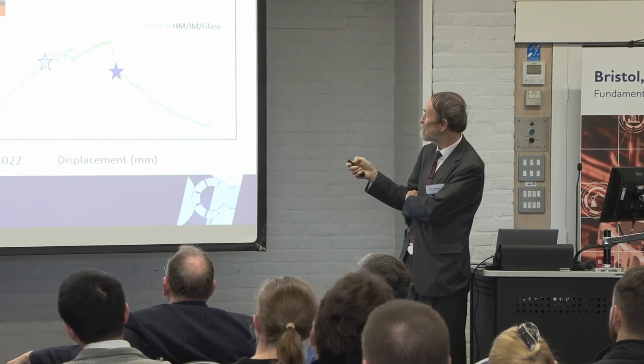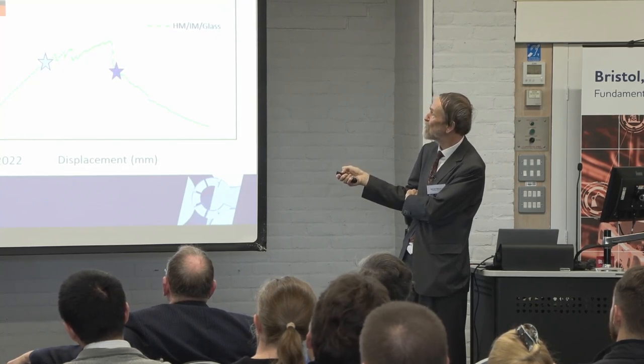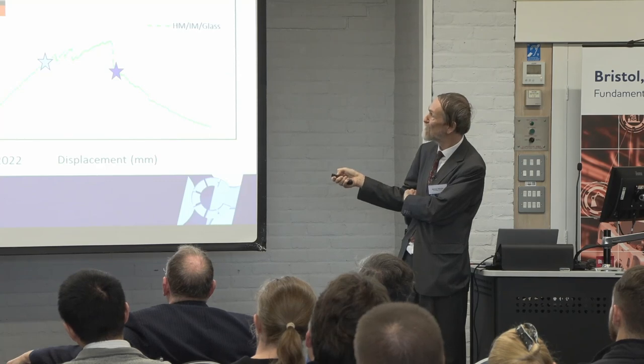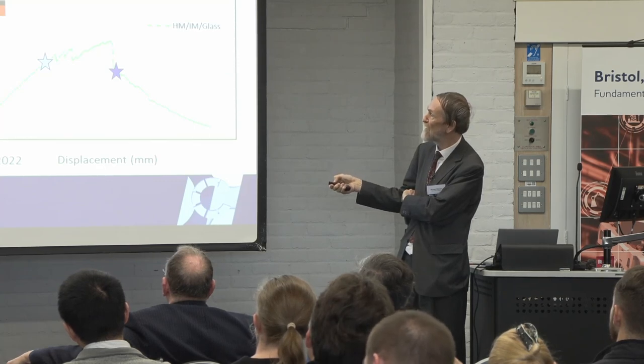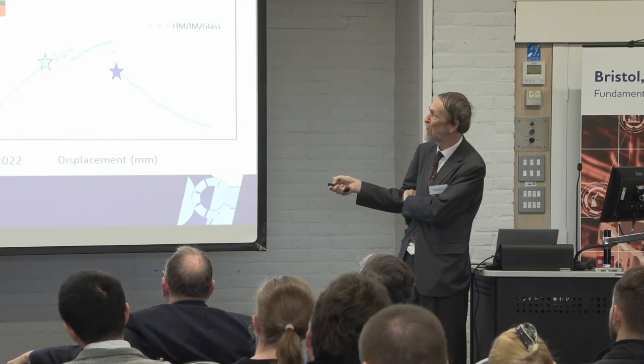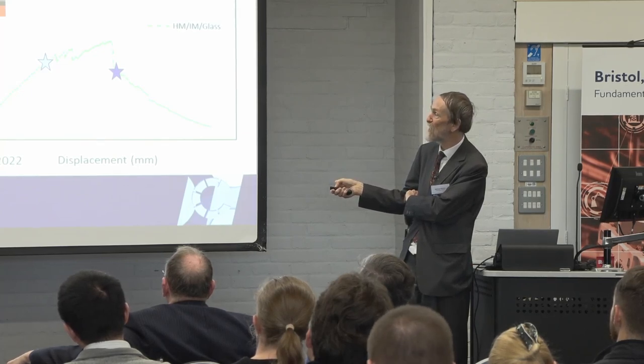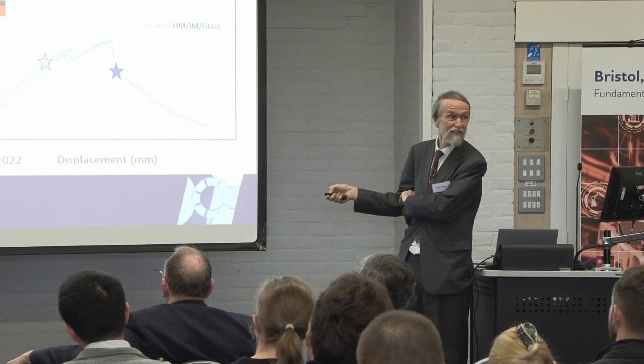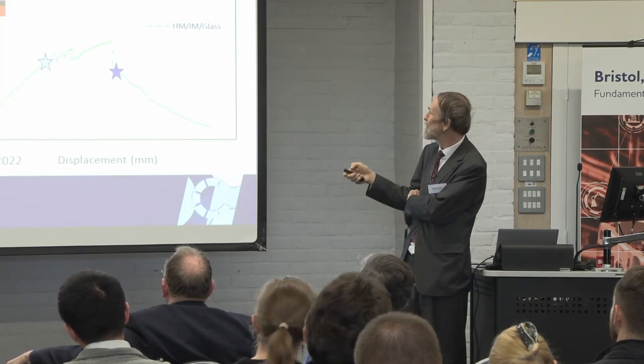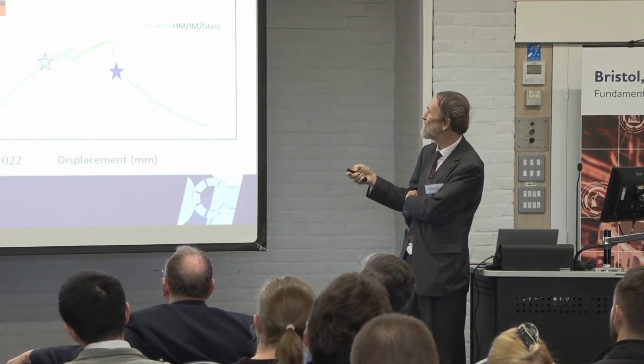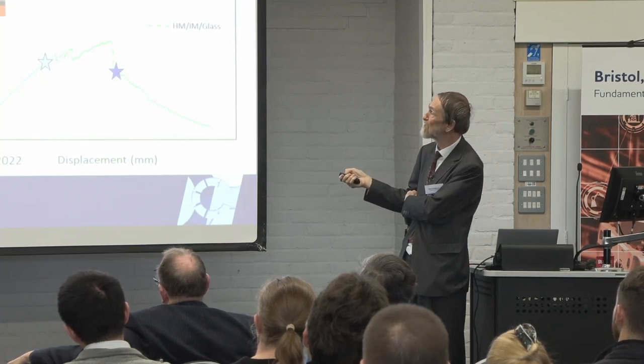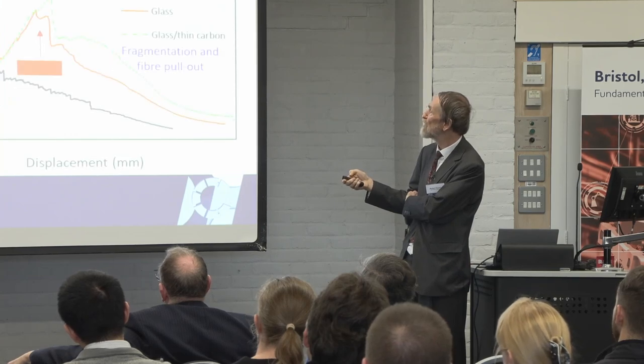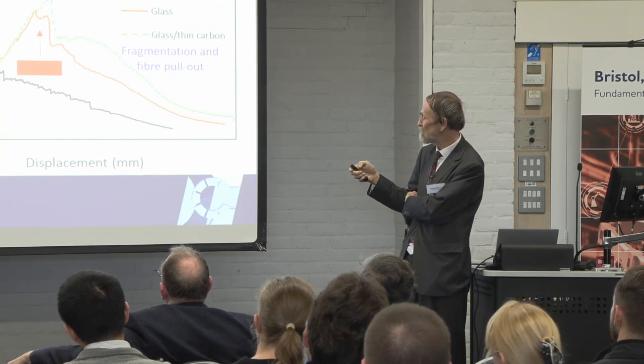And so when you go past this point here, what you can see is after this compression crack here, it started to fail all the way through the carbon, and we got a sort of a shear plugging mechanism, and then towards the end, the glass starts to fail in tension. So quite a complicated mechanism, and we also have delamination, which complicates the picture, but overall, we can see that we get a good response.